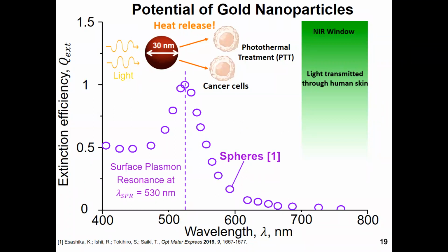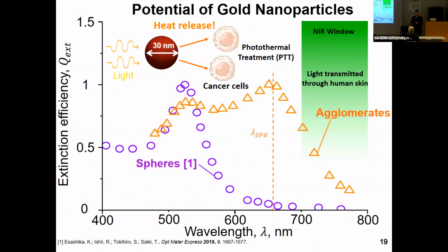However, with the flame technology that I showed you before, we can actually make agglomerates of gold nanoparticles similar to those that I showed you earlier for black carbon. Now, when you have clusters of such nanoparticles, their surface plasmon resonance enhancement is coupled. And for this reason, we have a second peak that's coming up, but it appears at larger wavelengths. And of course, it enhances the light absorption of these nanomaterials in the near infrared region.